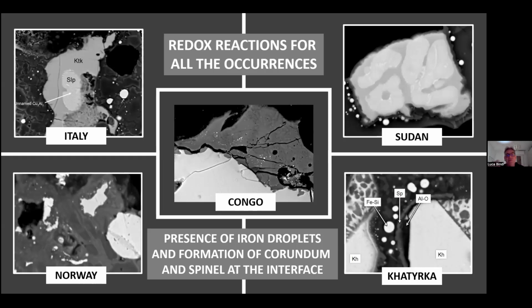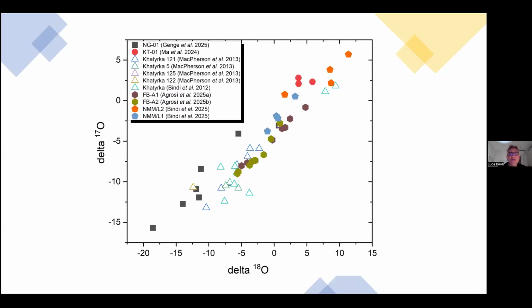At that time, we were able also to get the oxygen isotopes measurement of the new generation of spinel in the redox reactions. And again, they turned out to fall on the CCAM line, just indicating that the reaction occurred in outer space, which was actually pretty impressive. Well, so this is the image I promised you.